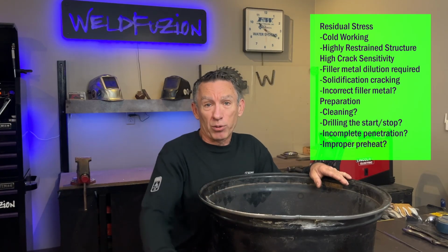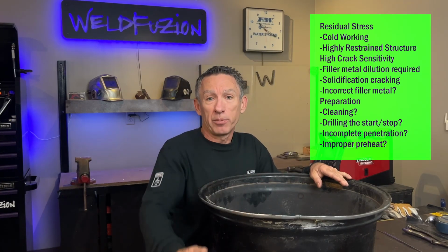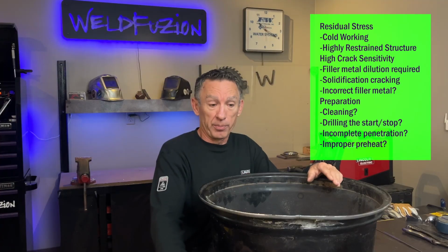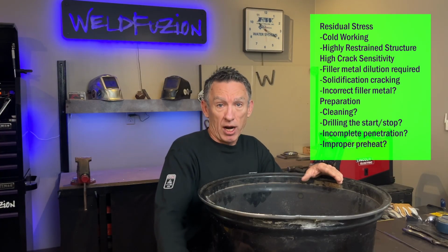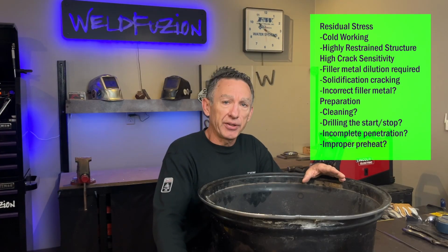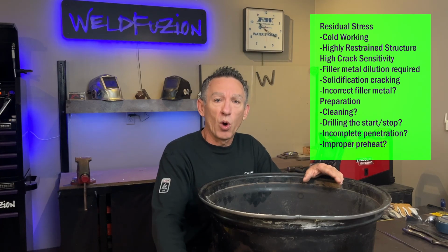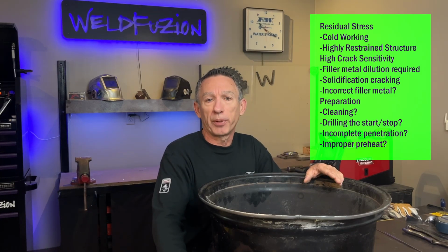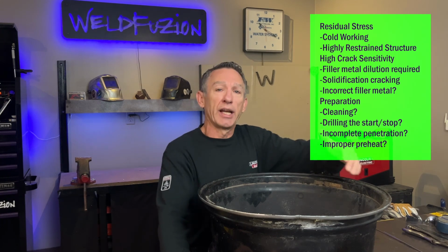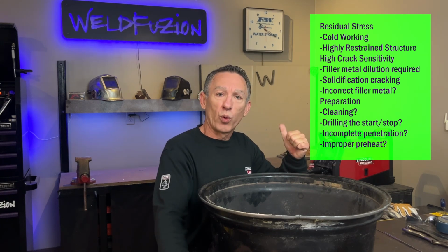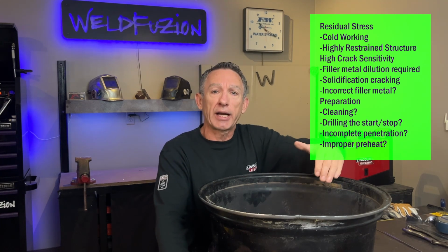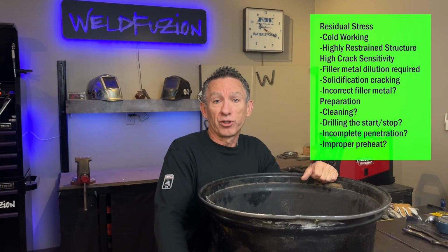Maybe they didn't clean it properly. They didn't get all the way to the bottom of the joint. Maybe they used the wrong filler metal. Maybe they didn't preheat it properly. There's a ton of different reasons why this thing could have failed, and what we're going to do as we work through this repair process to make it stop leaking is we're going to talk about each of those and how the steps that we take in our weld plan address some of the common things that would cause that weld to crack under nominal load. And hey, don't forget, shit happens.